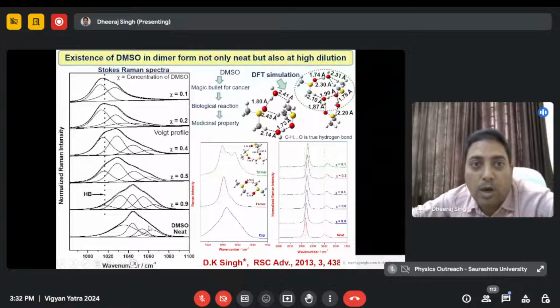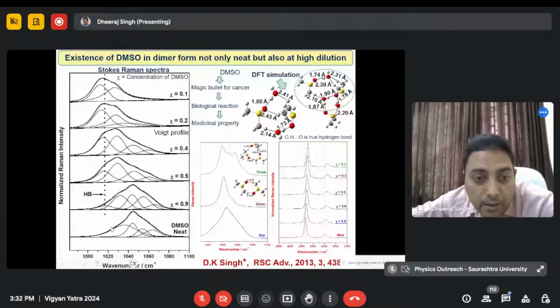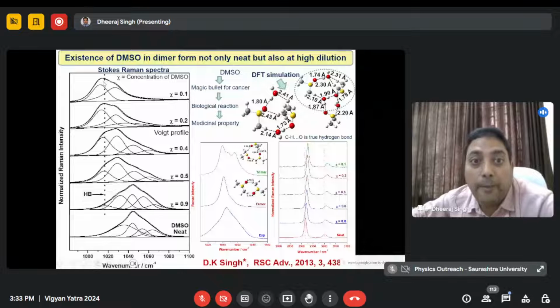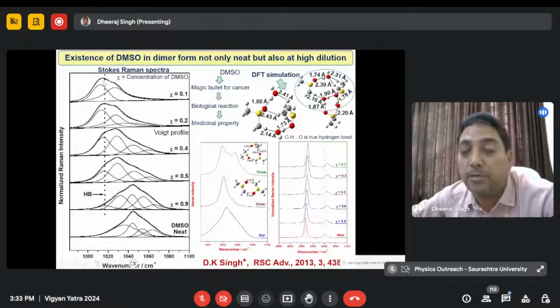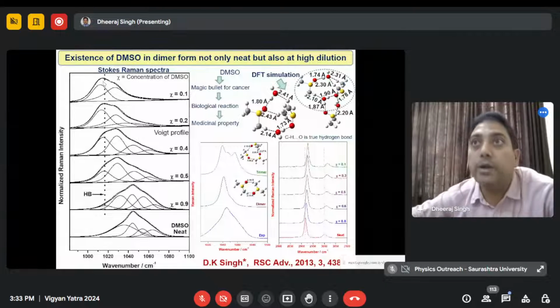And now when we mix water or methanol solvent in this DMSO, we can see that at the lower wave number there is no peak in the bottom spectrum. But when we increase the concentration of methanol or ethanol solvent, a new peak is generated on the lower side, and the intensity of this newly developed band goes on increasing from down to upside. You can see that at maximum dilution of DMSO with solution, we can see that.